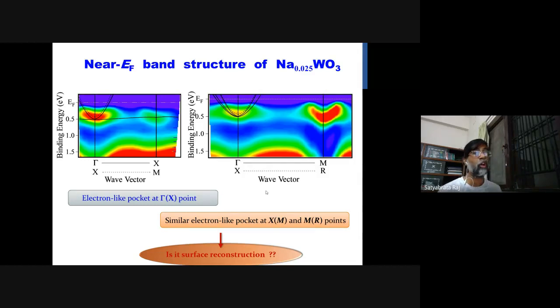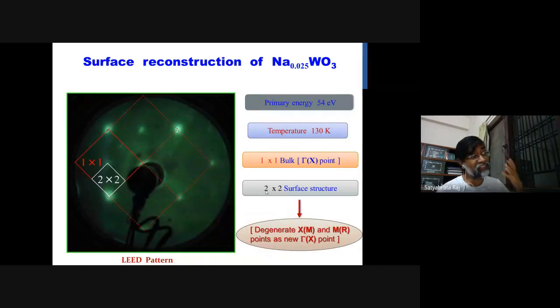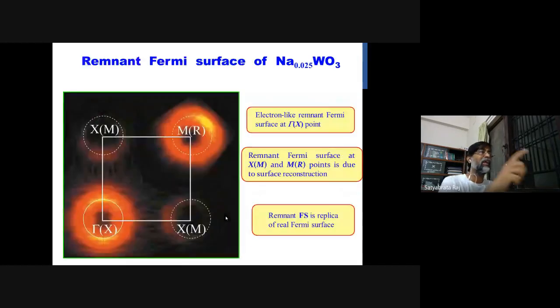Whether this is surface reconstruction or not, to understand this we have done surface-sensitive LEED, which shows a very well-defined 2x2 surface structure. LEED is very much surface sensitive, and this gives an idea that it can generate X and M points with a new gamma point. And as a result, the Fermi surface mapping gives us a Fermi surface at M and X points.